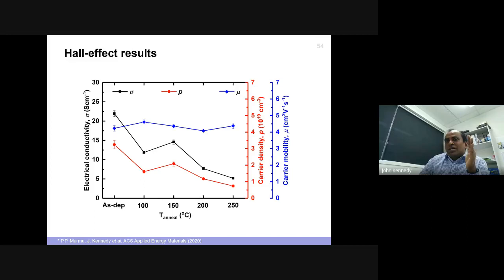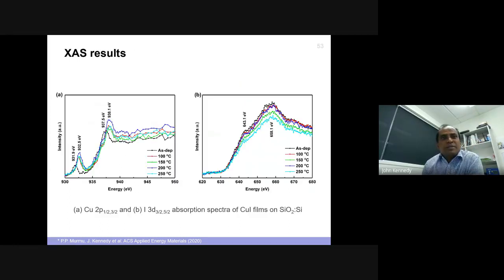While your carrier density is changing, your alpha is also changing. Your sigma is also changing. But if you put it in the context of the power factor, it's still not a big difference. Yes, it's very hard to control the conductivity, I agree. And the only way to control conductivity is to control the grain size. That's the biggest challenge we are facing. Does it make sense? Yes, sir.